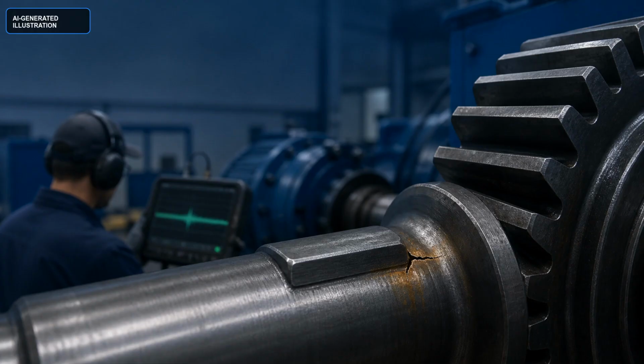This is not a disaster montage. It is a decision chain. In 2021, a routine inspection found a fracture along the I-40 Hernando de Soto Bridge, and the bridge was closed for repair. The FHWA account is about inspection and response, not a claim that this particular photo proves a fatigue mechanism. In a separate NTSB report, an alternator control gearshaft failure was attributed to high cycle fatigue, with intergranular corrosion cracking even though recorded vibration diagnostics were within acceptable limits. Different structures, same lesson. Normal-looking global signals do not cancel local damage evidence.